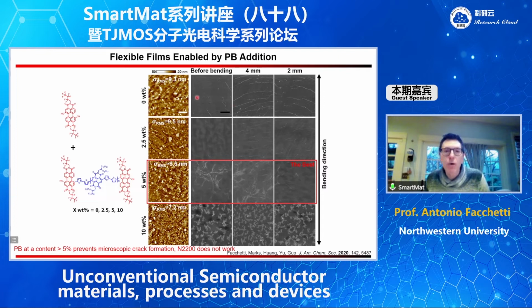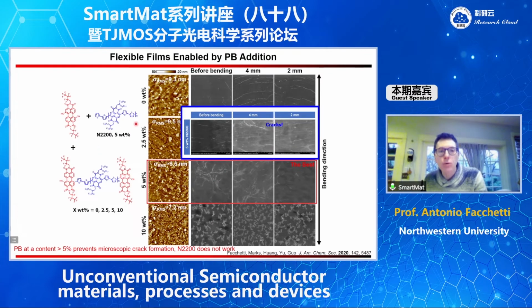And you see here that if you don't add any polymer, the film cracks. You add about 2.5%, it's still cracking a little bit. But after you put about 5%, you don't see formation of any crack upon bending. So 5% is a sort of optimal amount where there is no phase separation of the polymer and the film does not crack.